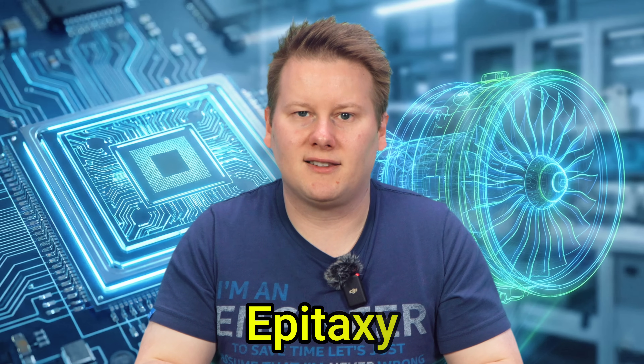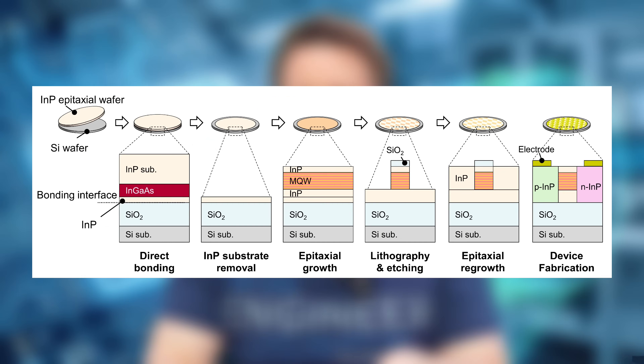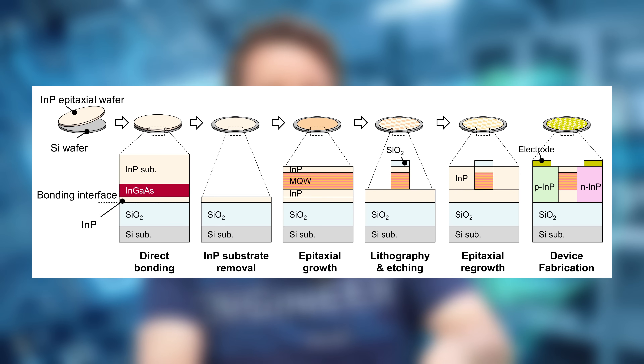The second process is called epitaxy. Sometimes we need to build structures with specific features and directions — for example, if we need to build on one plane of a crystal lattice. Epitaxy solves this problem by growing a crystal layer that matches the direction and atomic substrate layout. This is how channels and source-drain regions are set up with the right composition, including silicon-germanium layers for nanosheets. If we control temperature, pressure, and gas flow, we control the thickness and composition, where crystal quality is held uniform across the wafer for extreme consistency. Together, these methods are what enable scaling: ALD places precise dielectrics and barriers where the device needs them, and epitaxy sets channels and junctions with the lattice structure that you want. When structures move into three dimensions, this control keeps electron leakage in check and preserves key metrics like electron mobility and device-to-device variation.